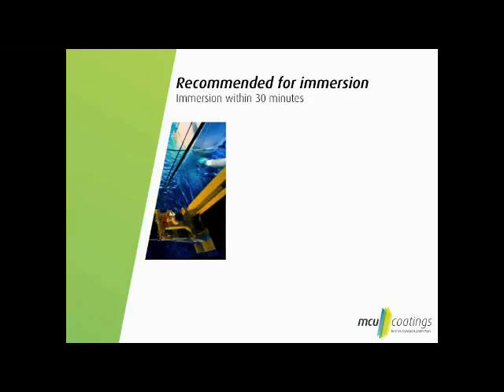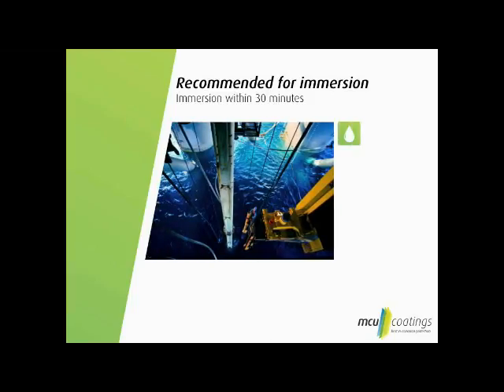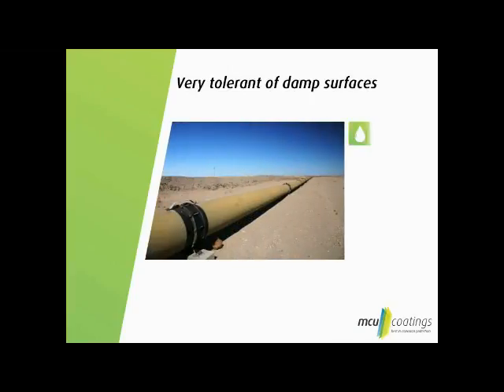MCU coatings are recommended for immersion and can be immersed or subject to fog, rain, or condensate within 30 minutes of application. Two-component urethanes are not recommended for immersion, and all conventional epoxies require 2 to 6 days cure before immersion. In cold weather, epoxies can require weeks. MCU coatings are very tolerant of damp surfaces, including gas pipelines and green concrete. Plural component epoxies and urethanes are not.